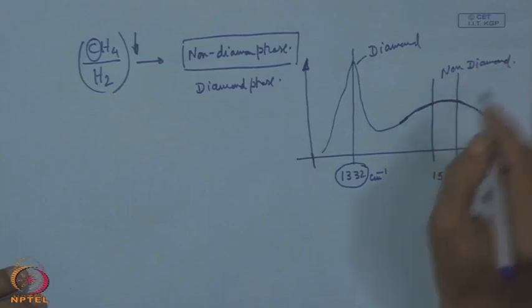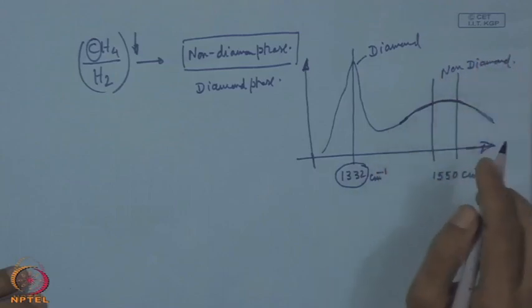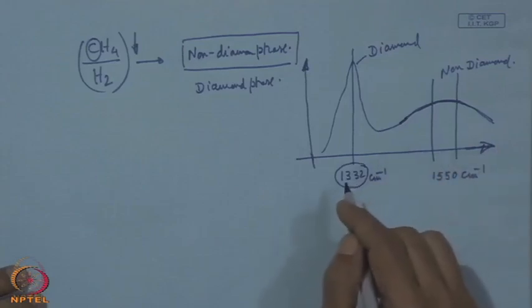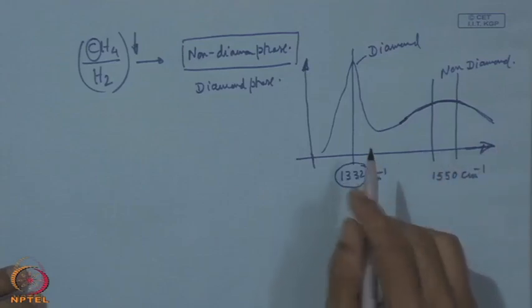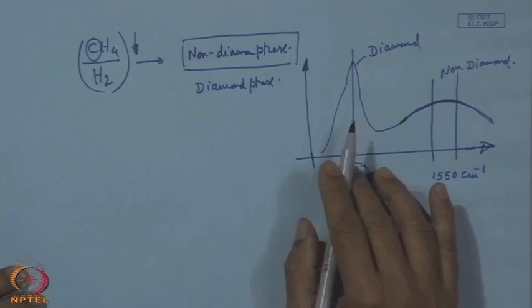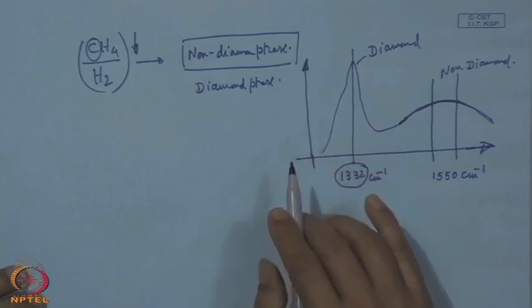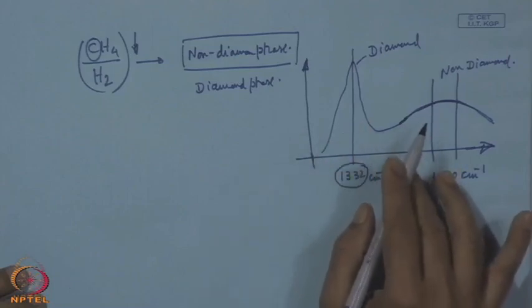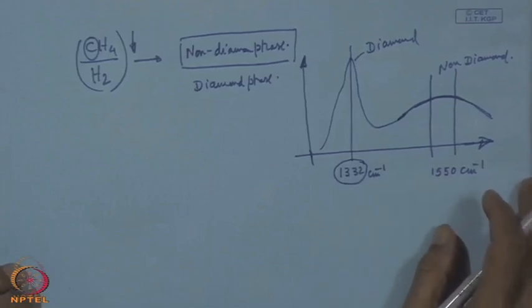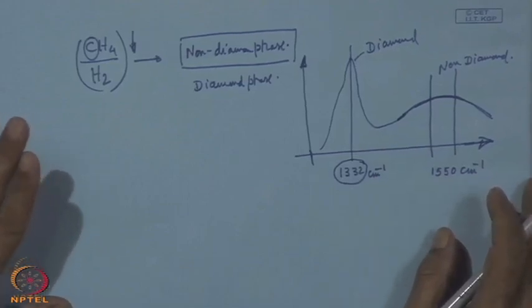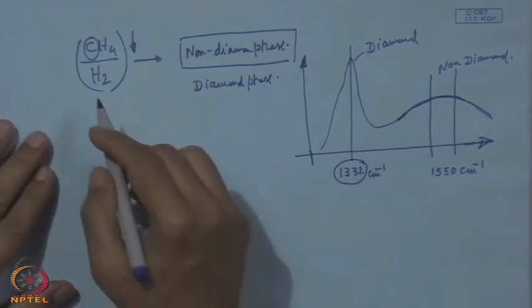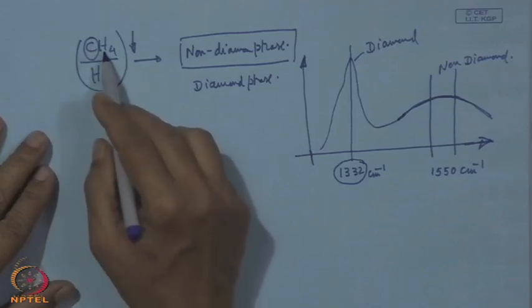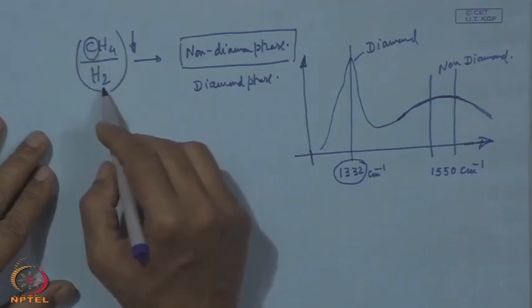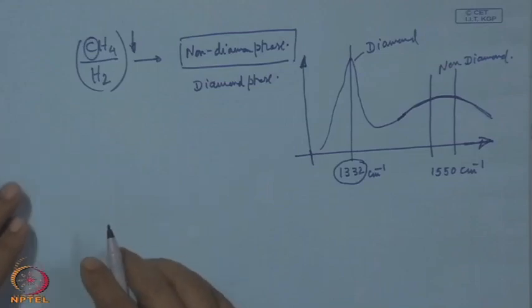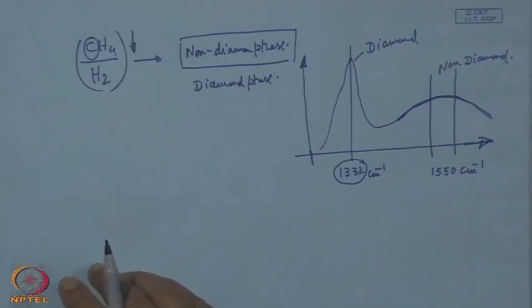After deposition, by Raman spectroscopy and Raman shift, one would come to know whether this coating has the diamond phase or a non-diamond phase. So this is one of the things which should be decided here in selecting the CH4 to H2 ratio. So, this is one important consideration.